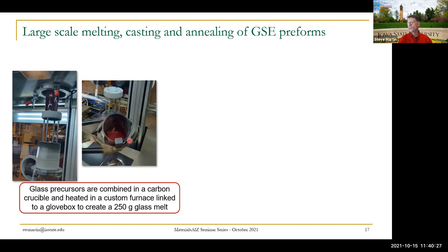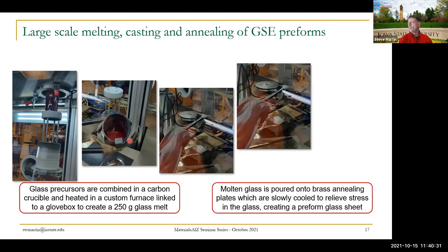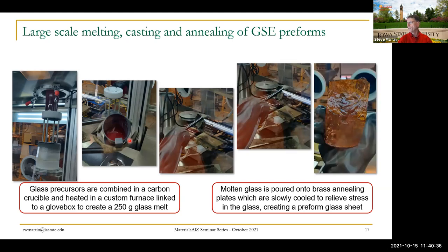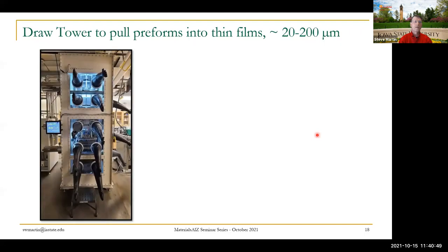We use vitreous carbon crucibles. They're very stable to these sulfide melts. And we just warm them up and we pour them out and we anneal them. And I think I've got a video, and then we get something like this. We get a large preform. This is one of the very first fast ion conducting glass preforms. You can see that here that we then melt. And then after we have the preform, then again, this is in our laboratory, we take that preform and pull it into a thin film. We just have a big old draw tower that sits inside an even bigger glove box.